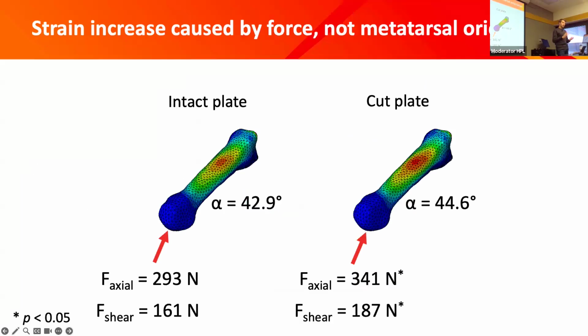Well, there are those two inputs that we can look at into the finite element model. There's the metatarsal orientation, and then there's the magnitude of force that we're applying. So in terms of the orientation of metatarsals, there's no significant change between the two. In the cut plate condition, the metatarsal angle for the second metatarsal is about 45 degrees at peak strain, and for the intact plate condition it is about 43 degrees, not significantly different. But there were significantly increased forces applied to that metatarsal head in the cut plate condition. So the axial force went from 293 newtons on average to 341 newtons, and that shear force also significantly increased from 161 newtons to 187 newtons.